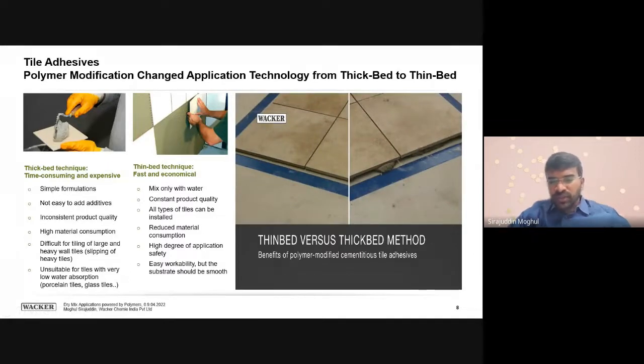So he is using the thin bed method and the thick bed method to lay the tiles. The thick bed method is the usual traditional method that we see, where we apply a mortar on the surface, on the substrate, whether it is on the wall or on the ground. We prepare a cement sand mortar and paste it on the tile or on the ground, and then we just keep it. And thin bed application is where we modify the cement with polymers, and we use a notch trowel to make it a thin bed, and then we adhere tiles onto it. You can see how drastic the difference in technology is, and how advantageous it is.